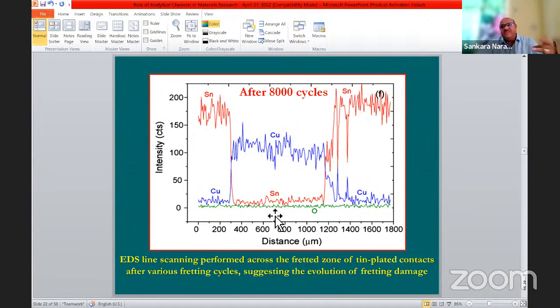Normally we can say that tin is highly conductive. Why is the resistance increasing? Because tin is a highly conductive metal. But the moment tin is removed and tin and copper are exposed to oxygen, they may form tin oxide and copper oxide. These oxide materials are poorly conducting. So that is why your contact resistance is increasing.